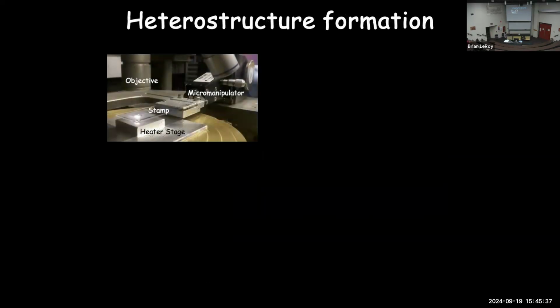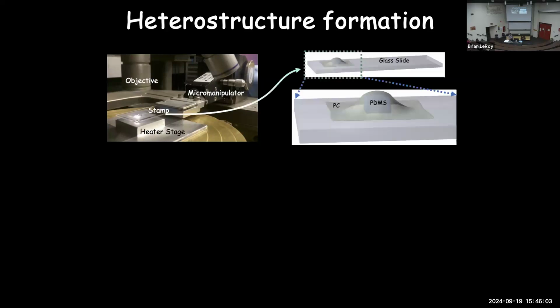And so the way we do that stacking is with a polymer stamping technique. What you can see here is a microscope objective. We look down here. We bring a little plastic, basically saran wrap, on the end of a glass slide here, and we bring that down into contact with our sample. And we can peel off the 2-dimensional material that we're interested in looking at.